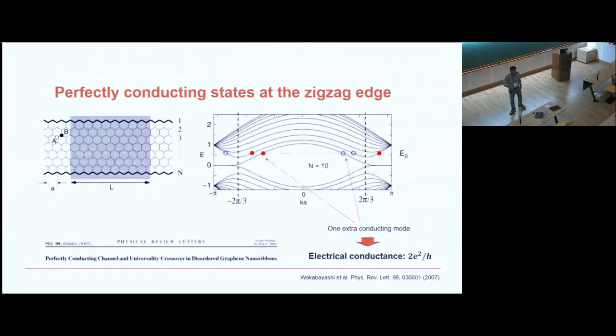And this is what has been done. And this has been done by many people over the last 20 years. What seems to be the case is that if you have a band structure with a zero energy state and you keep the Fermi energy somewhere here, then you have one additional state moving in this direction on this edge, and the other state moves in this direction on the opposite edge, leading to a perfect electrical conductance. This is the theoretical prediction. Okay? It has not been observed so far. The question is, how can we do this?